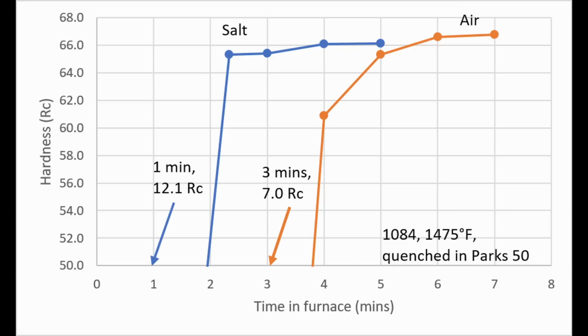Now, the required time in the furnace is not just to heat up the steel, it's also to dissolve the carbides. So the steel gets to temperature, and then we hold it there longer to dissolve carbide, to put carbon in solution, and then the hardness is related to how much carbon we had in solution prior to quenching. And at different temperatures, this will take different amounts of time. So I was using 1475 Fahrenheit, and at that temperature, especially with 1084, dissolving the carbides is pretty fast.